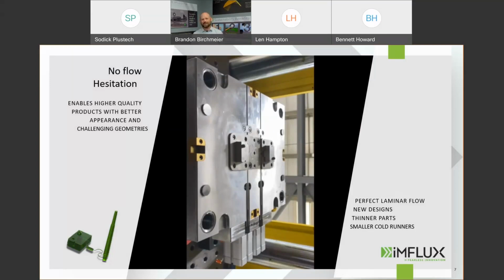What happens with the iMFLUX process is geometry is dictating our velocity. So at a constant pressure, I'm filling that large sprue out pretty quickly. You can fill out pretty quickly. There's not a big resistance to fill there. But as soon as I hit that thin gate, I slow down dramatically, and we slowly fill through the runner system to reach the thick section and then speed back up again.